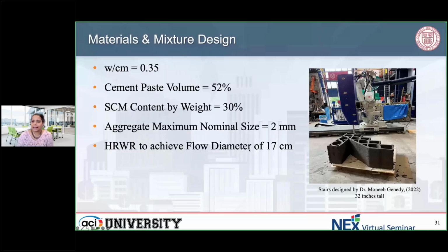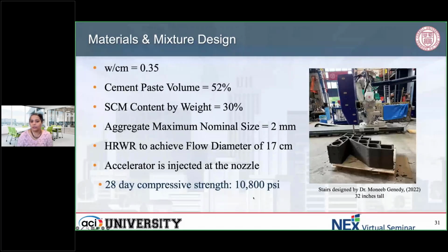And then we inject an accelerator at the nozzle. So inside this box over here, we have an injector where the chemical gets injected, and then it gets sheared in and just comes out of this metal nozzle right here, and the material gets deposited. So our material has a compressive strength of about 10,800 psi, so it's really strong, and we also have a very good flexural strength of about 800 psi. And we also did a bonding test to make sure that the layers have a very good bond strength, which is why we were able to use these as steps.